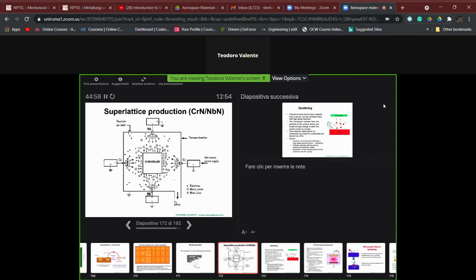That's a case instead by using sputtering. It's a special case with which we can fabricate quite special types of coatings that are called, then we will see there are also commercially available solutions, superlattice coatings, made of special materials, nitrides, this is chromium nitrides and niobium nitrides, in the form of multi-layer coatings.